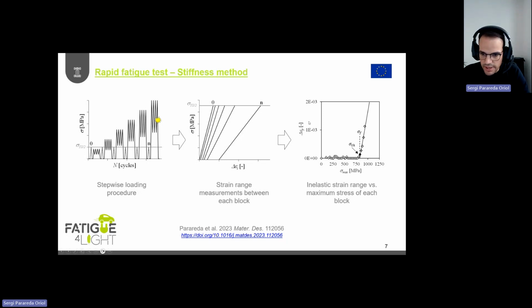By plotting, on the right-hand side of the slide, you can see the plastic strain, which is related to fatigue damage, against the maximum stress of each one of these fatigue blocks. In this case, we can clearly see how the strain is evolving. So the fatigue damage is evolving at a given stress value, and this stress value is the fatigue limit of the material. But the good point is that since we are monitoring the fatigue damage, we can not only define the fatigue limit, we can also define the slope of the SN curve. So we can obtain a complete characterization of the fatigue resistance in a short time.